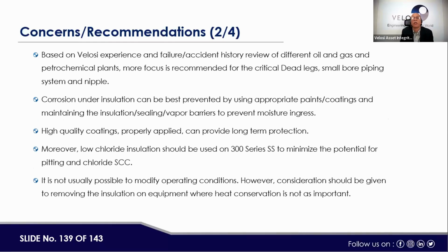Corrosion under insulation can be best prevented by using appropriate paint and coating and maintaining the insulation or sealing vapor barriers to prevent moisture ingress. High quality coating, properly applied, can provide long-term protection. Moreover, low chloride insulation should be used on 300 series SS to minimize the potential for pitting and chloride SCC. It is not usually possible to modify operating conditions. However, consideration should be given to removing the insulation on equipment where heat conservation is not very important.